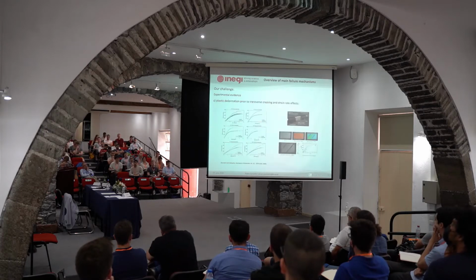Now, the problem is that if you go to Abaqus or to any other software, and you want to predict first ply failure, and you don't take this into account, you're not going to distinguish between thick and thin. So you're not going to capture this difference in terms of the onset of transverse cracks. Okay, so this is something that we also need to take into account if we want to have good predictions of strength in composites.